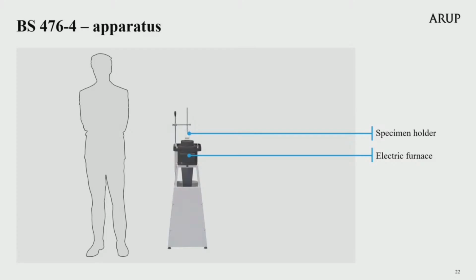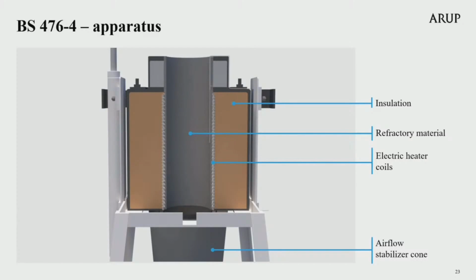A second thermocouple is placed in the centre of the specimen, inserted from the top. This shielded thermocouple shall maintain contact with the material at the bottom of the hole, drilled down halfway into the specimen. The image on screen shows a cross-section through the furnace. The key thing to observe here is that the heat is provided by running electricity through wire coils wrapped around a central tube made of alumina refractory material. No direct flame impingement occurs in this test.